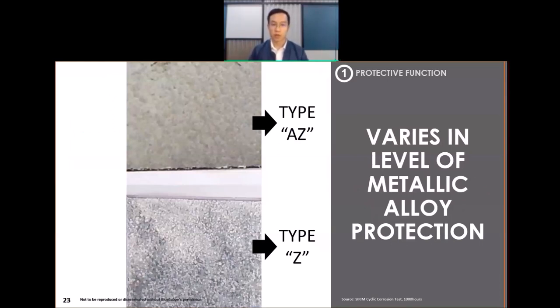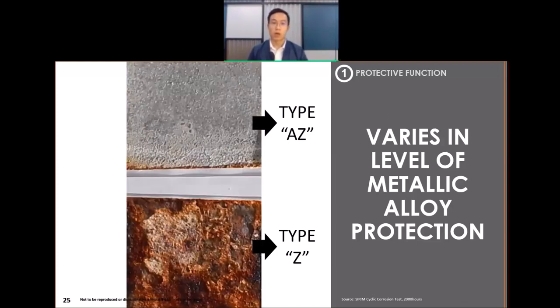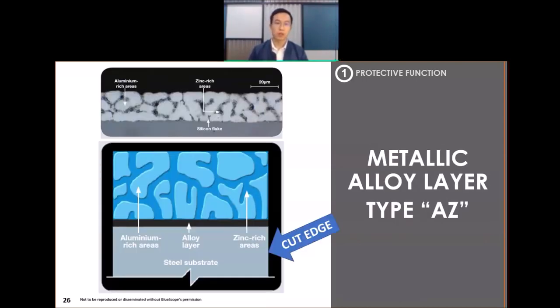We have done many tests over the years - in one of the more recent ones, you can see that choosing different types of galvanic coating affects the lifespan and protection capability of the whole steel finish. A less optimal coating will show rust in a shorter period of time. The more typical one supplied to the market is the AZ coating - a metallic alloy layer employing both aluminium and zinc - which provides galvanic protection by sacrificing itself to protect the steel.